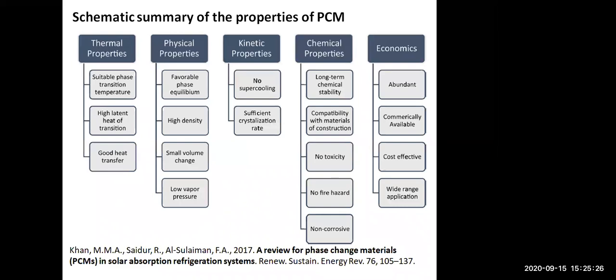Then properties of phase change material. The thermal properties, like the melting and solidification temperature of the PCM, are in the range of deciding operating temperature conditions. Then a latent heat of fusion that is higher with respect to unit volume compared with the sensible heat. Then specific heat and thermal conductivity in solid and liquid phase must be high for enhancing heat transfer rate. Then kinetic properties, like a relatively low degree of supercooling, or less or no supercooling. That should be no supercooling exhibited by the PCM.